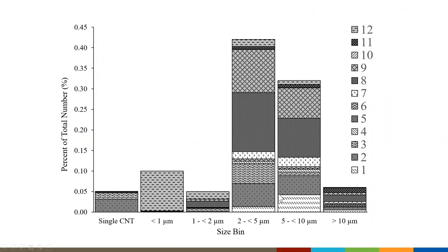And this is just to give you an idea of what size we were typically seeing as far as the agglomerate and single fibers go. So on the x-axis, you can see the six size bins that we chose for our transmission electron microscopy analysis. And then the y-axis is the percent of total number of the structures that we counted for all of the 200 samples that we collected from all participants. So you can see predominantly about 80% of the samples were greater than 2 microns. So this is telling us that most likely these agglomerated materials are going to fall within the thoracic or inhalable size fraction, as opposed to these single fibers, which you can see will only comprise about 5% of the total sample set. Next slide, please.